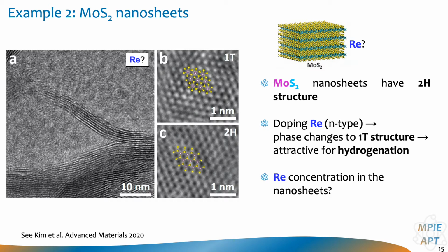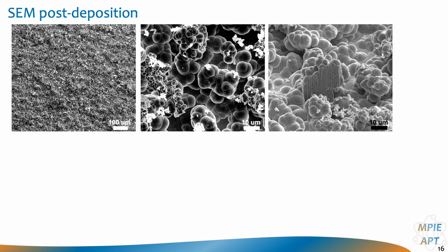And so we dispersed some of these 2D nanosheets inside of the electrolyte, and then electrodeposited it. The surface in that case doesn't form a beautiful homogeneous film, but these agglomerates of nickel. And this can be understood because the nucleation of the nickel crystals will start where we have the agglomeration of the nanosheets at the start.